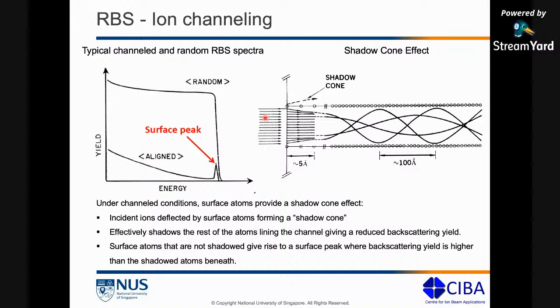Most of these incident ions will enter the channel, except for the ones that collide here and here, which will backscatter from the surface atoms, which is why in a channeling spectrum you will have a surface peak. That is why we call this a surface peak. So this is a very characteristic feature of a channel spectrum. If you don't get this peak, then that means your channeling is not good. You're having some problem with channeling, or it's not a single crystal anymore.